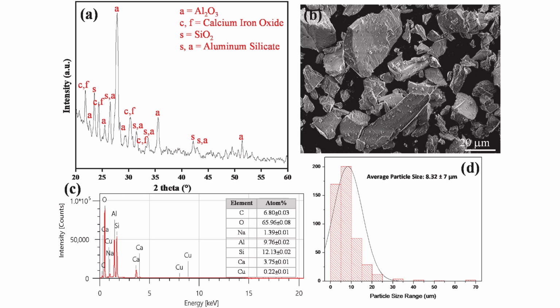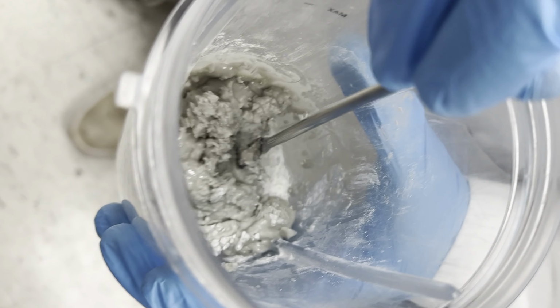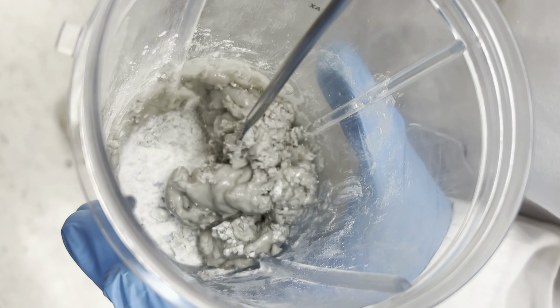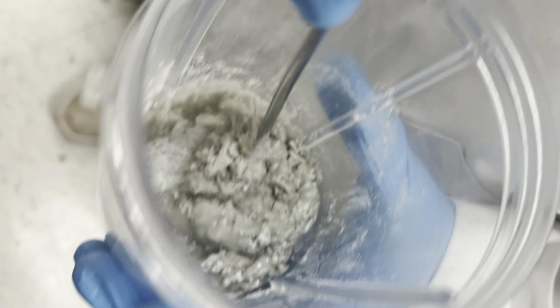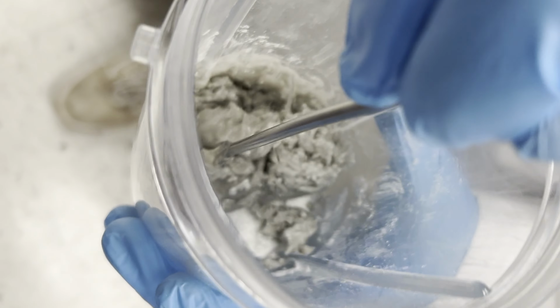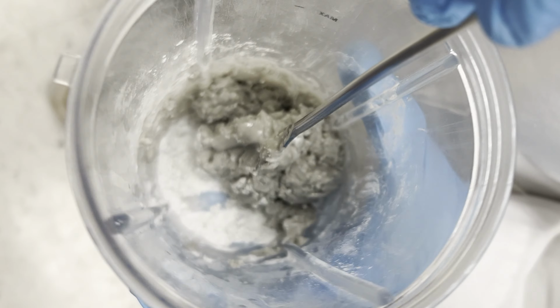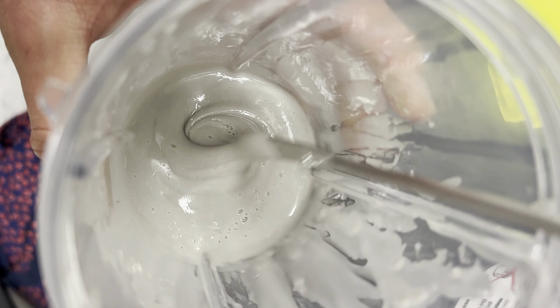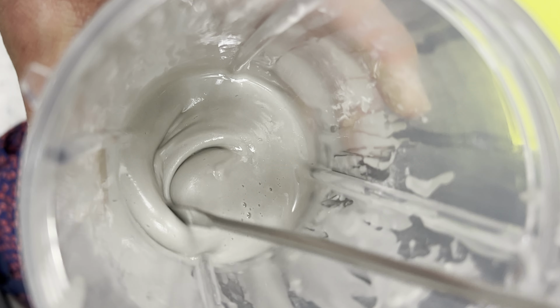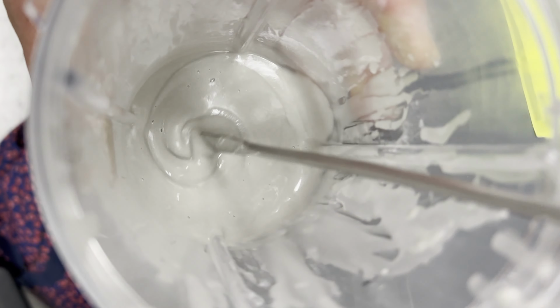It has an average particle diameter of approximately 8 microns plus or minus 7 microns. The regolith has to be mixed with a photocurable resin in a concentration that allows for good flowability. At 70% regolith and only 30% resin, the slurry shows poor flowability. At 60% regolith and 40% resin, the slurry shows excellent flowability.